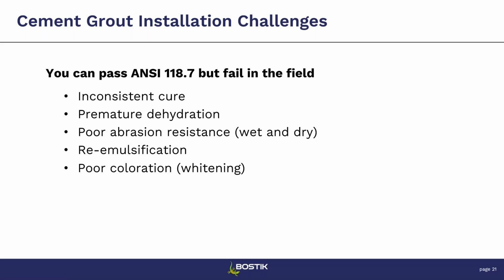So some of the challenges you may find as you're installing is you can pass the ANSI 118.7, but still fail in the field because of that inconsistent cure. So again, you have that with the humidity, if it cures faster or slower, depending on that. Premature dehydration, poor abrasion resistance, whether that's wet or dry. Re-emulsification, and emulsification is defined as a liquid being dispersed in small amounts and then being re-emulsified, or again being done and having that happen a second time. And then of course poor coloration, which is the whitening of a grout. So as the grout fades, it comes up to a lighter color.